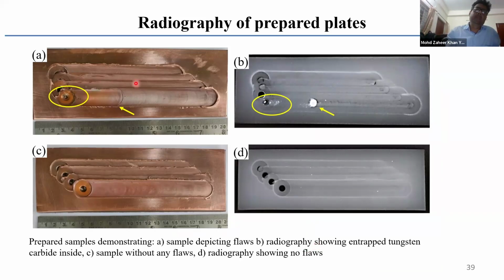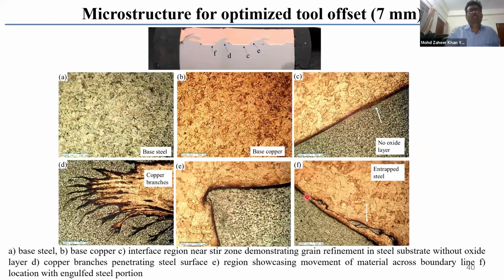As you can see, if the parameters were not right, these defects can occur, and you can see this is a defective plate, and this one is a defect-free plate. No defects are actually obtained. This is the microstructure and macrostructure. You can see very firmly the mild steel and the copper plate has been anchored.